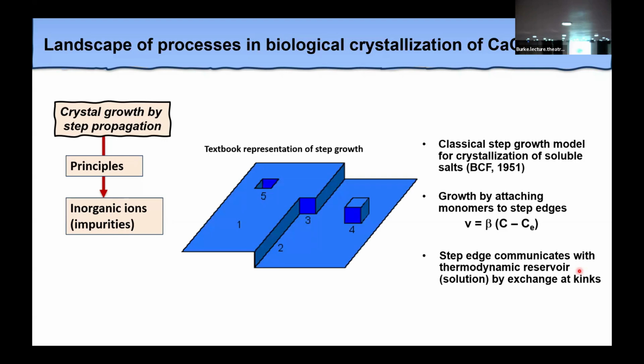Okay, here we go. All right, so here's classical crystal growth. This is what you see in the textbooks. And this is what we were going on. Everyone was going on it. The classical step growth model is what's called Burton-Cabrera-Frank theory from the 1950s. And basically the velocity of step motion is determined by the rate of ions coming out of solution and attaching to these step edges, either at kinks or forming new nucleation sites on the step edge. And you can measure that by AFM, at the angstrom scale. And the relationship is just the velocity of the step motion is given by some kinetic coefficient, and that's related to the departure from equilibrium.